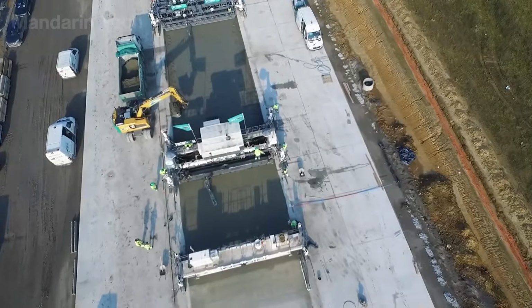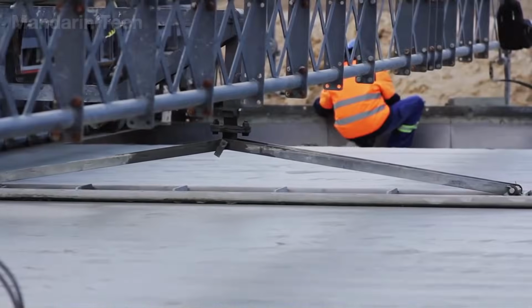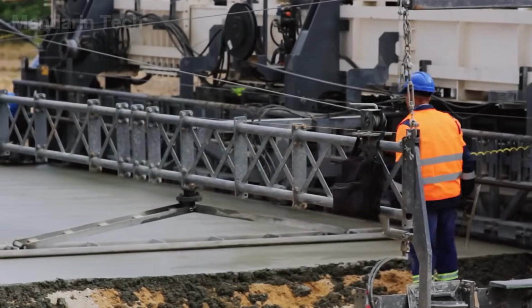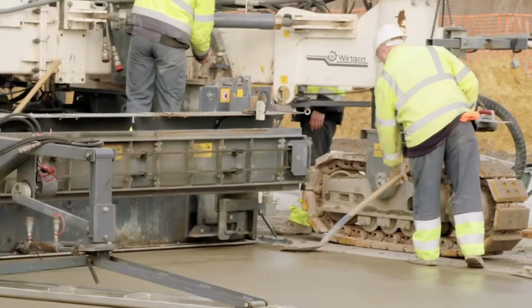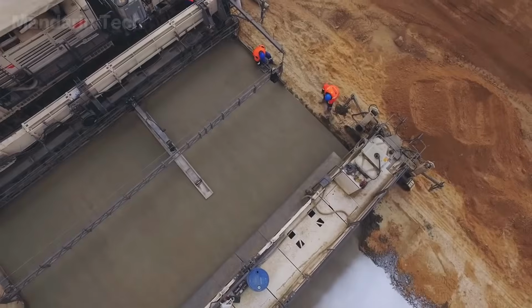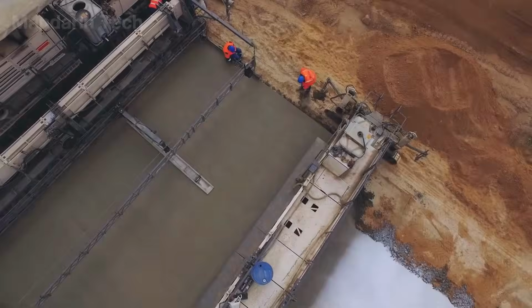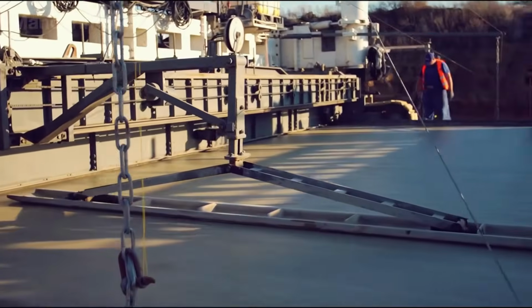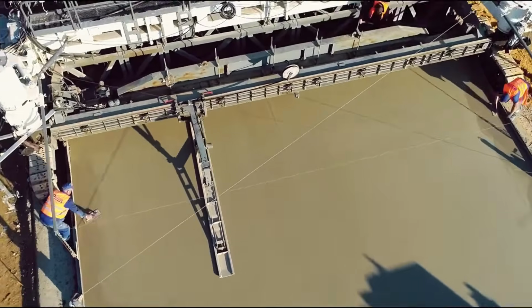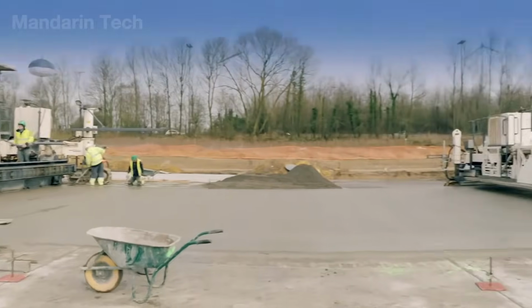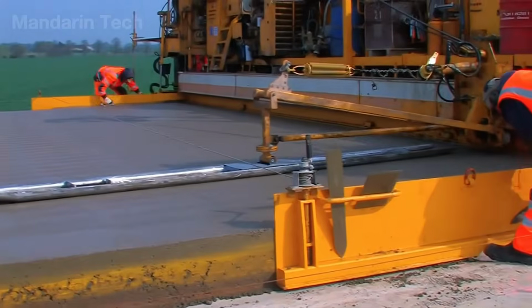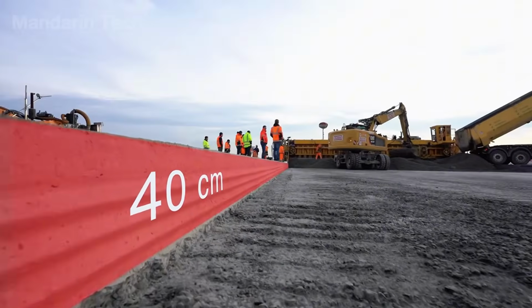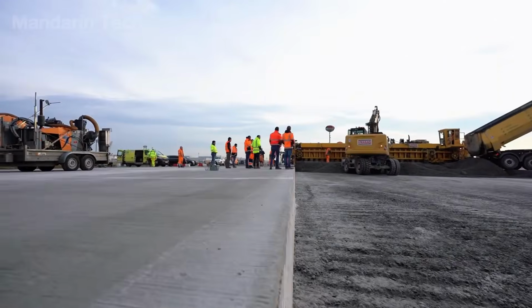Right after the concrete is shaped, long finishing arms sweep across the surface to smooth and lightly compress the top layer. These blades ensure the concrete surface is free of waves and achieves the required high-speed roadway finish. This step is crucial for maintaining long-term ride comfort and skid resistance. When completed, this concrete layer is usually about 40 centimeters thick.